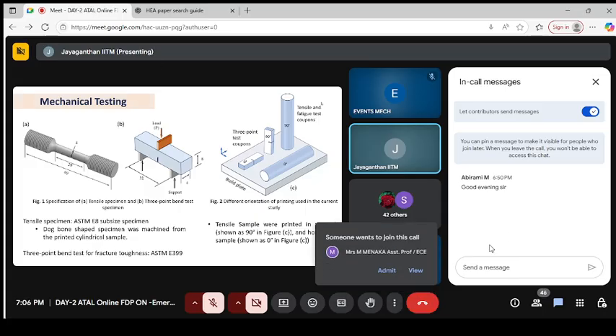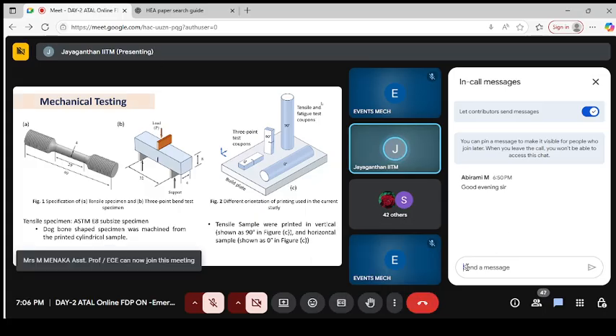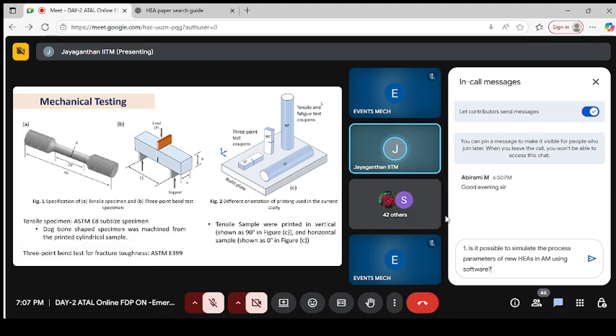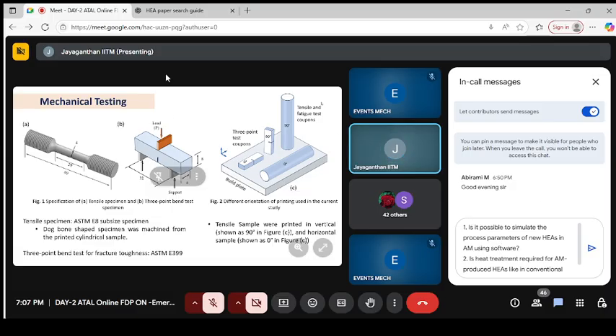Again, you are all aware of how we do hardness testing and tensile testing. We have ASTM standards for tensile specimens, where we can have rod samples or plate samples as per ASTM standards. If you want to do a fracture toughness test, you can use a 3-point bend test, or you can even use a CT specimen. And again, the sample is fabricated either vertically built or horizontally built. The orientation matters, so we used different orientations of the printed samples. Tensile samples were printed in the vertical direction as well as the horizontal direction, because we want to know whether orientation is going to matter for the final properties of the 3D printed material.